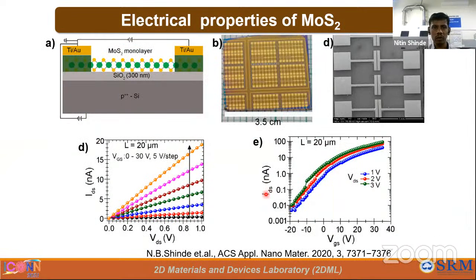We also studied the electrical properties of our deposited sample using a back-gate field effect transistor. This is the schematic of our transistor, and this is the actual picture of the device. We varied the channel width from 20, 50 and 100 micrometer, and calculated the field effect mobility and on-off ratio of our device. We are getting an on-off ratio around 10⁴, and mobility of 0.1 centimeter square per volt per second.